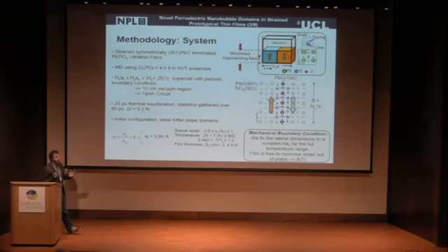But we also wanted to look at the misfit strains. We can do this without affecting the degrees of freedom of any of our atoms, just by fixing our simulation box. So we use this canonical ensemble, and by fixing the shape of our cell, we can change our misfit strain values. Basically the idea being that for a fixed strain value, we can increase the temperature and see what domain patterns we get. And does our model agree with the literature?